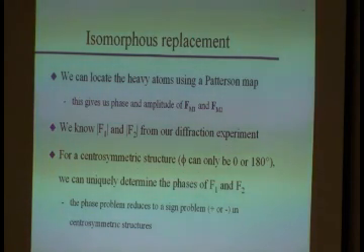If I have a big protein, and there's one heavy metal in it, or maybe two, is that going to be the major contributor? The rest of the electron density is not as localized as the one in the heavy atom, but if you look at the total number of electrons in a unit cell, that heavy atom is no longer as dominant. Okay? So that's why you might have to play these tricks.